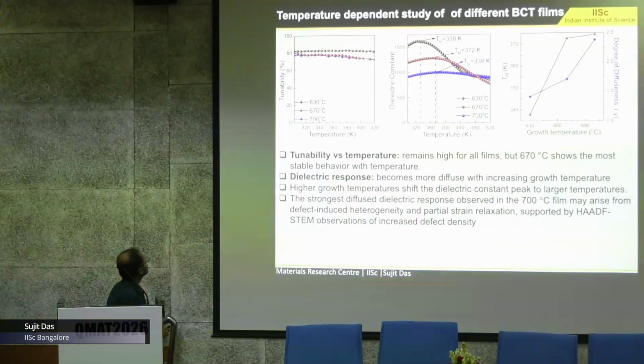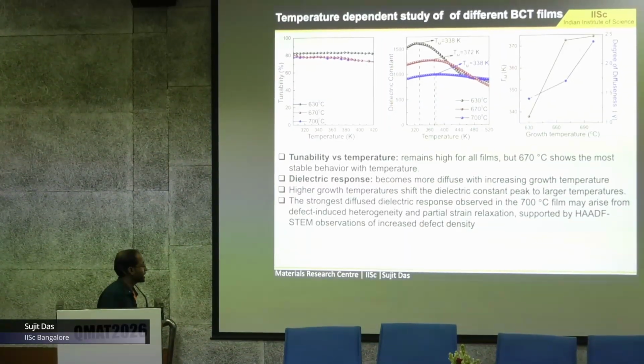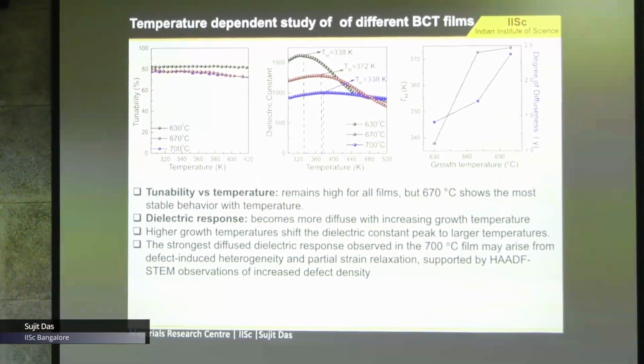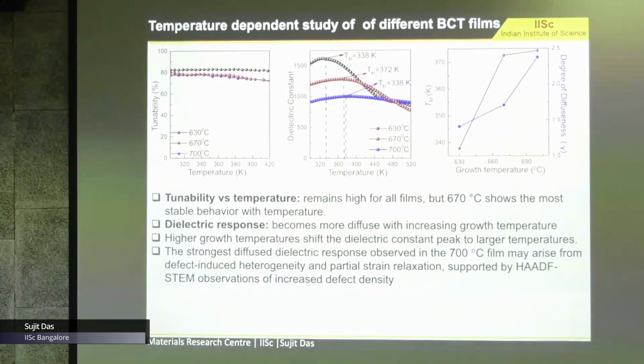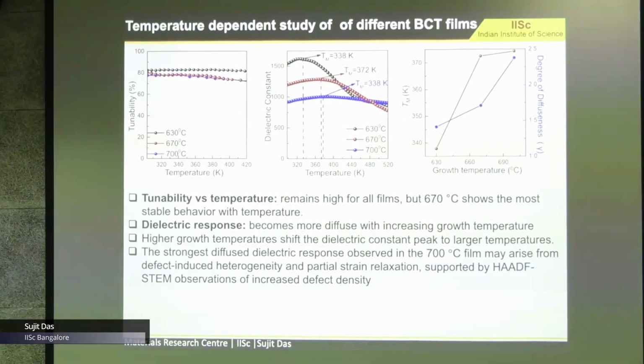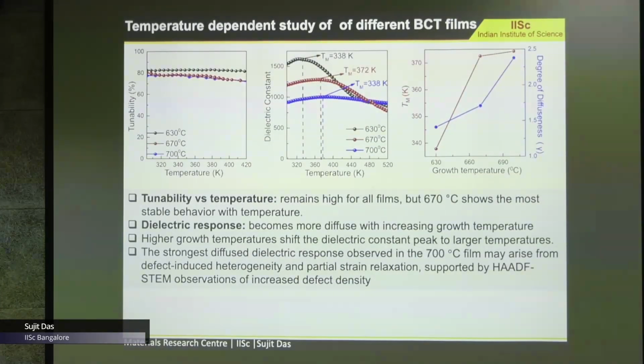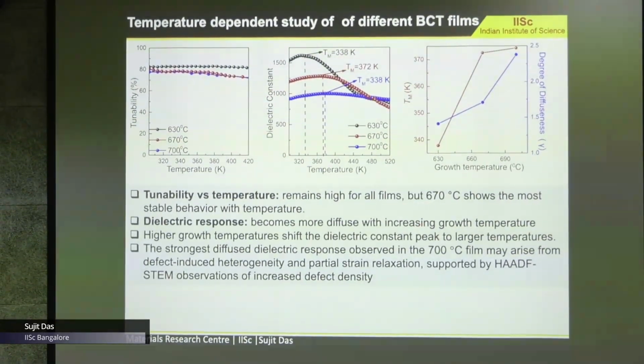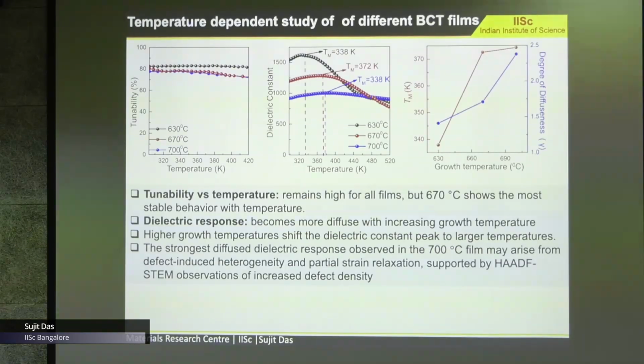So now we check the stability of this tunability with temperature. We found all samples showing good temperature stability. And if you look at the phase transitions, again the phase transition is pretty broad, but the transition temperature is enhancing with the growth temperature. This transition is showing a diffuse type of behavior, and we calculate the diffuseness, which is higher for 700 degrees C. This could be because the film grown at 700 degrees C could have defects, induced heterogeneity and partial strain relaxation. That could be the reason for this high diffuseness.